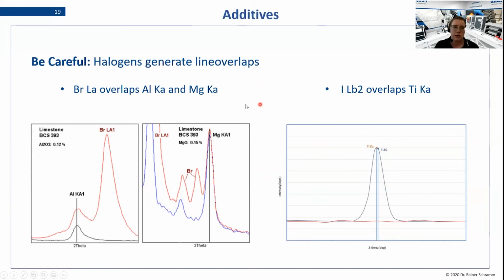I'm having two examples here. One time we are having the bromine L alpha line that overlaps with aluminium K alpha and magnesium K alpha. We can see it in the graphics down here. The black one here is a limestone sample that was fused without bromide, and the red curve displays a sample that was fused using bromide, and we can see that the aluminium K alpha peak is significantly higher here. The same goes for the magnesium K alpha peak here. Again, same sample, one time in blue without bromide and one time in red with bromide. And also here, we can see an increase in intensity in this peak due to the bromide concentration that is there.